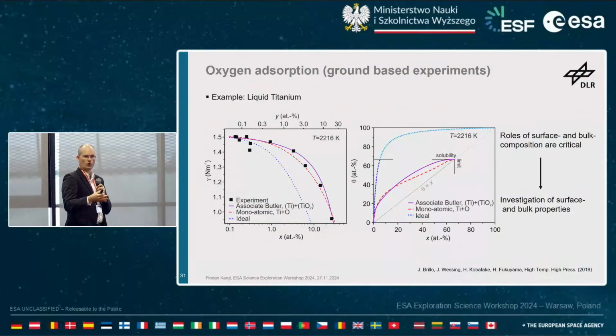And at a certain point, basically when a certain content is exceeded, then the oxygen, of course, starts to accumulate at the surface, and then it has an impact on the surface tension. Can be described well by the associated Butler monoatomic model here. And the ideal description here is clearly deviating.